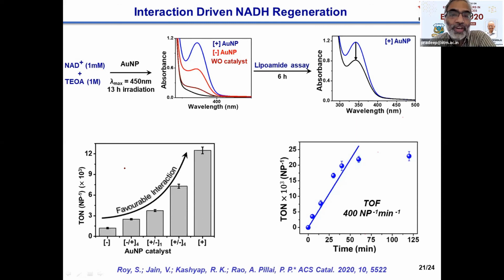Connecting to Samir's talk, it might be depending on the number of surface gold atoms. Active gold atoms. No, Pradeep, this is more about absorption cross section. The more the number of gold atoms, the more is your absorption cross section. And this was not on the 2D sheets. This was another work we did with gold nanoparticles, cadmium selenide tipped with gold nanoparticles. So it really depends on the number of gold atoms. Here it is basically the hot electron chemistry, which directly depends on the absorption cross section.